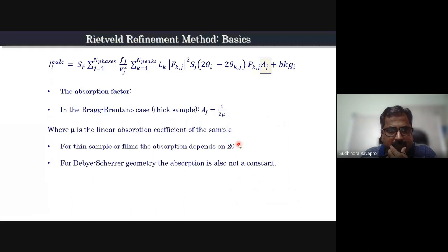Okay, and there is something called the absorption factor. This is mainly useful, or comes into the picture, when you are working with the transmission geometry, because the radiation passes through the sample and the chances of it getting absorbed are very high. It matters less with neutrons, but if you have a very thick sample, or the sample is not properly aligned, in case of X-rays it is possible that some portion of your beam is getting absorbed within the sample, and that has to be corrected at some point.